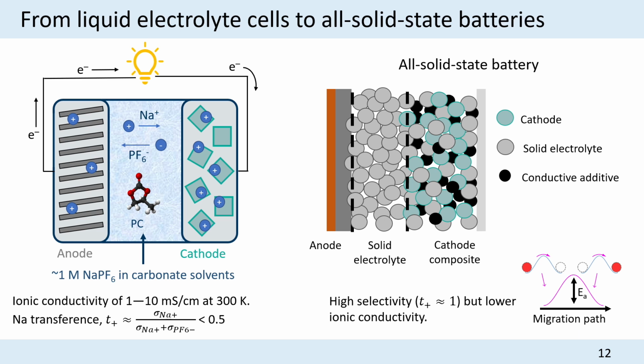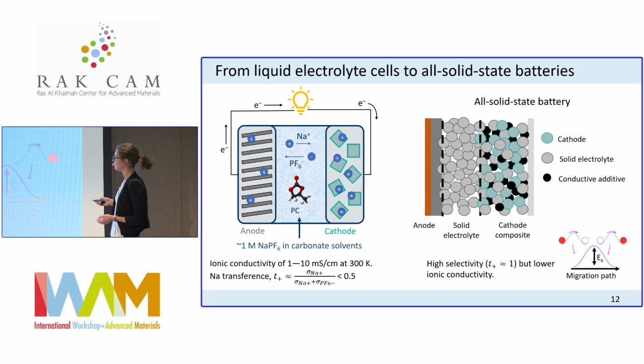In the solid state, when you have sodium diffusion, you typically have sodium hopping from one site in your crystal structure to the next, and it has to go through this energy barrier, so you really want to find a material that has a low migration barrier for sodium.